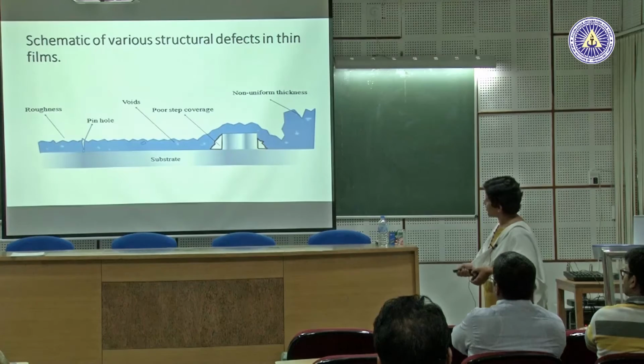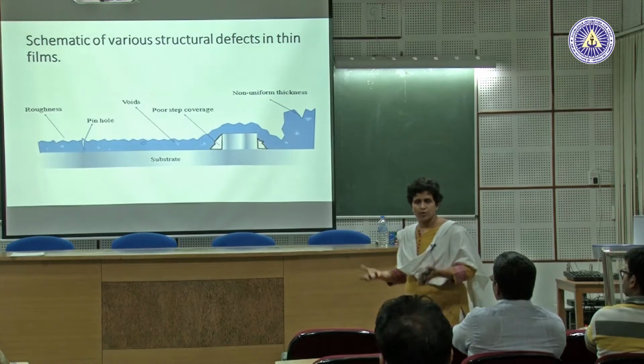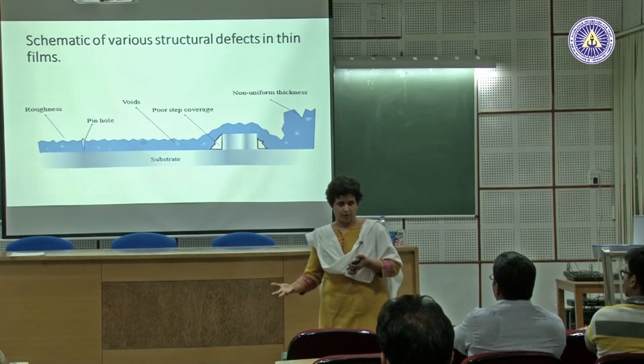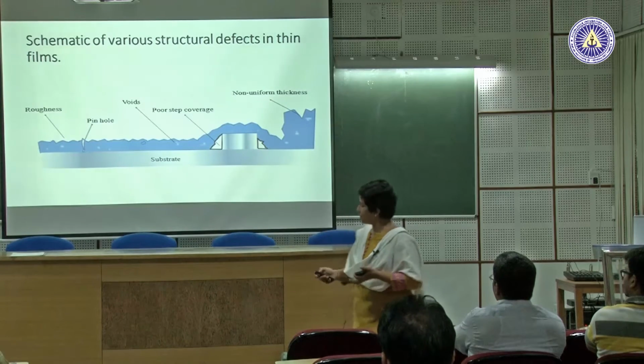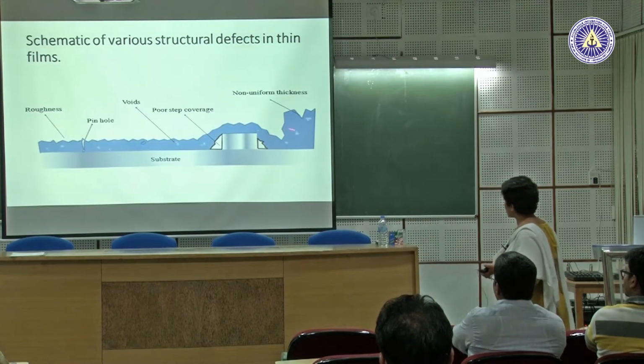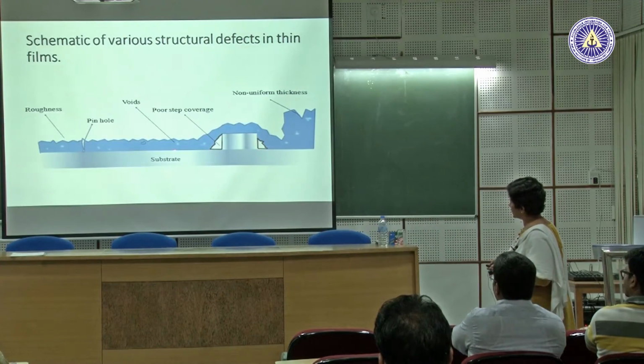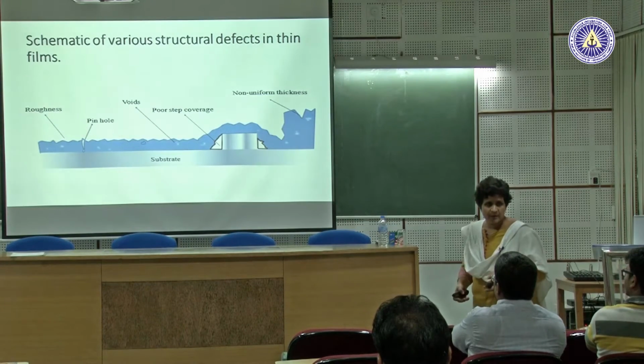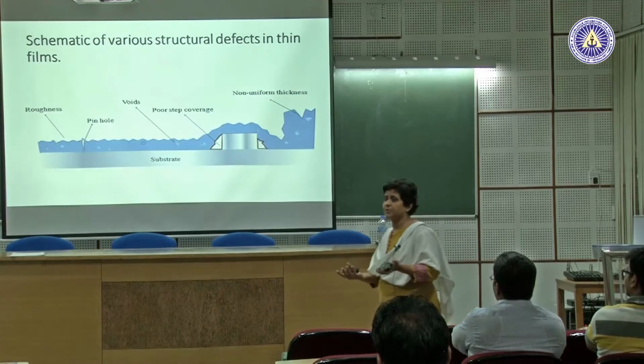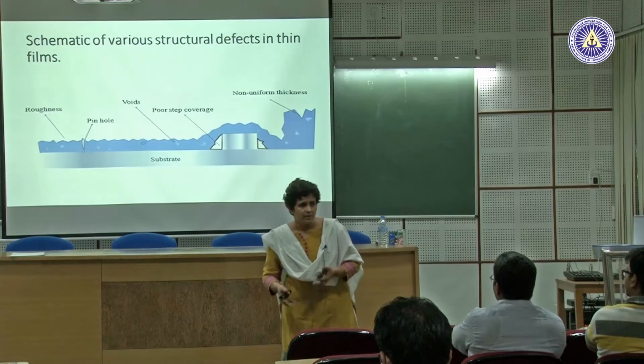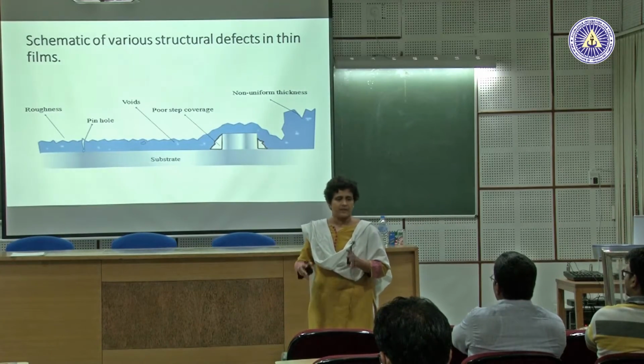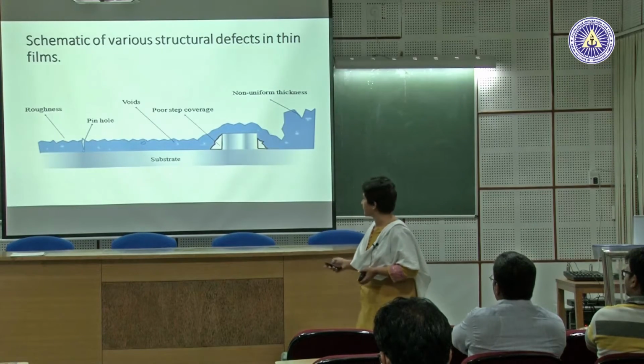And these are some of the problems that you normally see, and then you have to control your material and process parameters. You would see a film not being conformal, there are voids, pinholes, roughness, all these could be problems depending on your application. Roughness can be bad for optical applications. So, all these issues can come up, and then you control your film deposition technique to handle that.